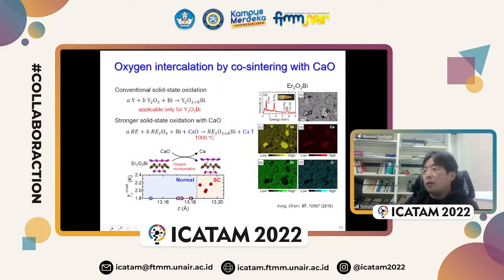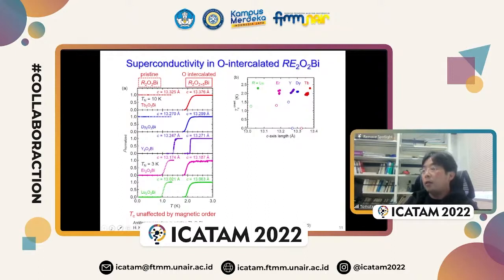As a result, we succeeded in oxygen intercalation in various R2O2Bi. So this is a summary. This is the temperature dependence of the resistivity of R2O2Bi. This is a pristine R2O2Bi, in this case Tb2O2Bi. This is not superconducting, but by introducing the excess oxygen, this becomes zero resistance. So this is superconducting. In the case of dysprosium, this is also superconducting by oxygen intercalation.